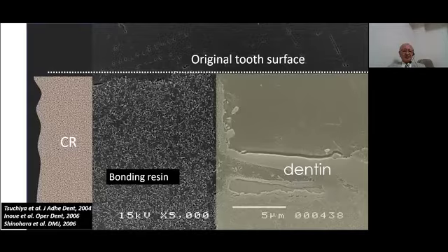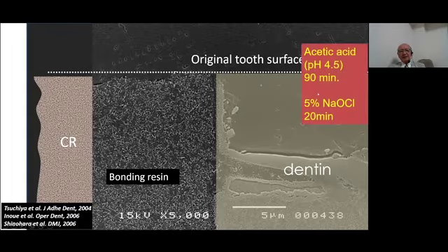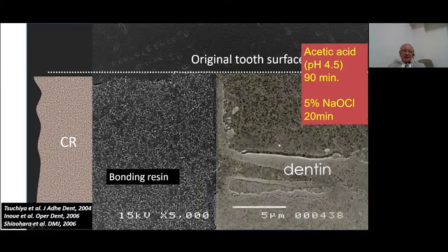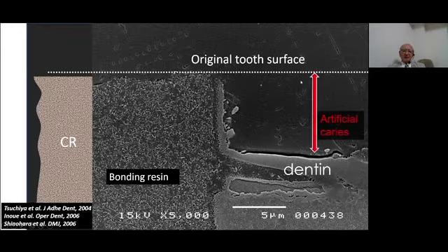Okay. So this is the original surface. Composite resin is here, and bonding resin is here. This part was the dentin. This is the tooth surface, and the interface is here. At this bond interface, we applied the weak acid and the basic solution to create the artificial caries. That's why dentin was dissolved. This is the depth of the artificial caries at the restoration margin.